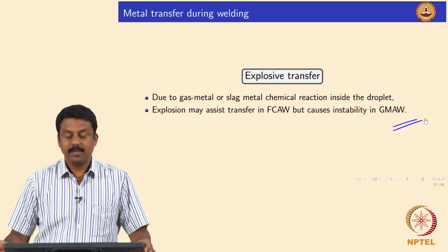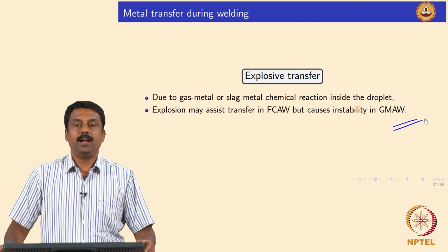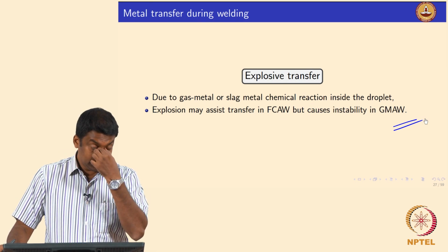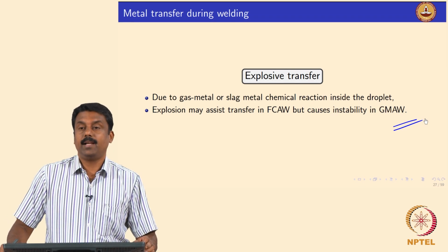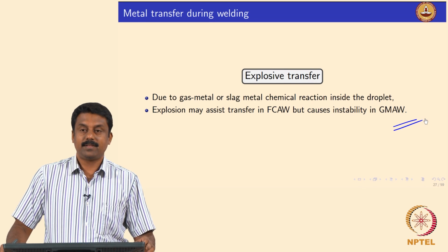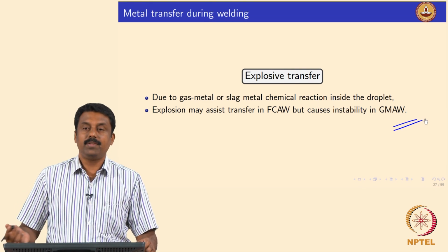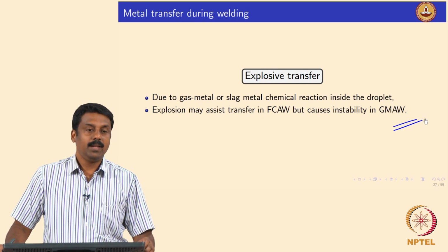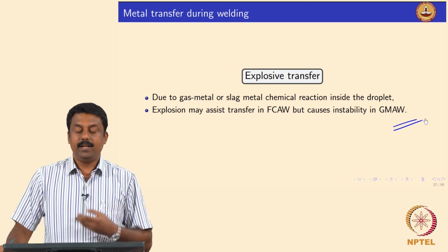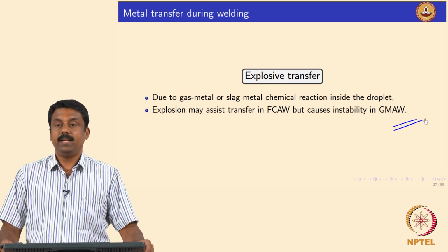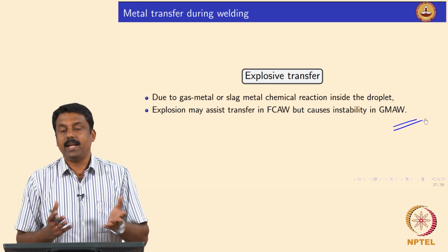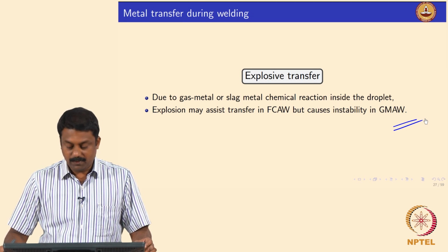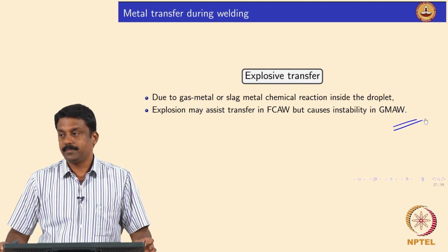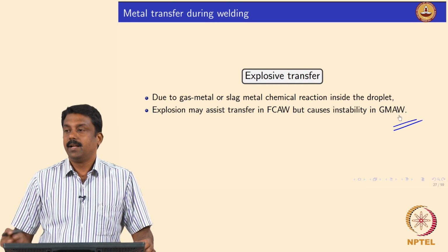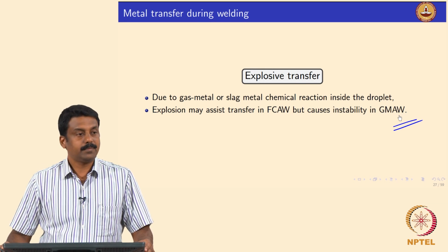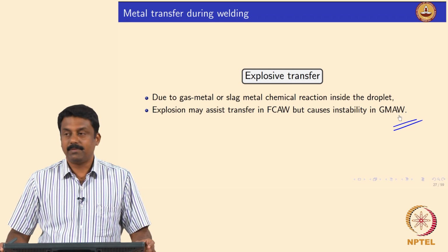In some cases, if you increase the current tremendously and you also have a shielding gas generated, especially in self shielded electrodes, you may have an explosive transfer. Most of the cases, it happens in self shielded or flux core arc welding electrodes, where you have a very high current and a gas generated by the flux, and the gas pressure is contained. So, you increase the plasma jet pressure and the Lorentz force, and you may expect an explosion of the droplet. It is an extremely unwanted mode of transfer, because you can never weld by explosive transfer.